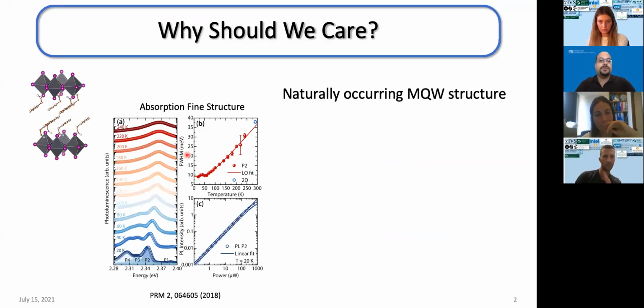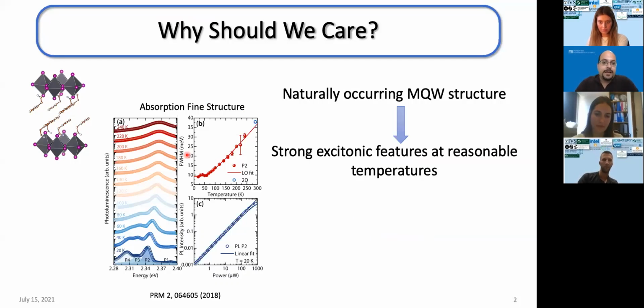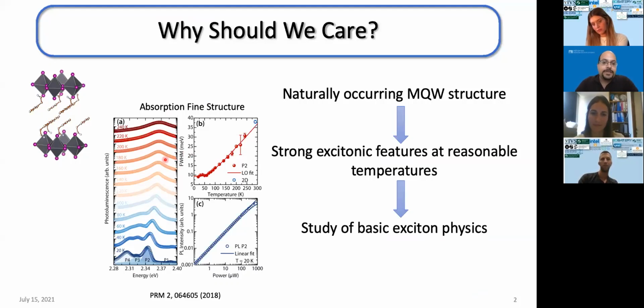Now, why should we care about 2D perovskites? They form naturally occurring multi-quantum-well structures, meaning that as a result, they exhibit strong excitonic features even at reasonable temperatures, as you can see here, for example, from the absorption spectrum of a 2D perovskite at different temperatures. And for this reason, they are a great playground to study basic exciton physics. Excitons are the most basic many-body problem that we can study,